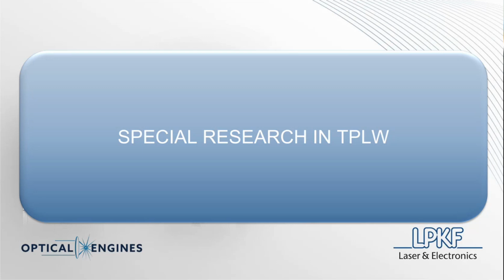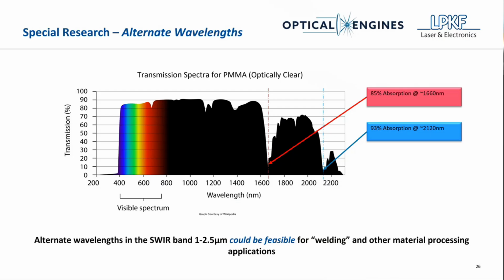So I wanted to cover a few special research topics in transparent polymer laser welding, some of the cutting edge stuff, and basically just educate and let people know that there are some options we have here, and we're working on testing. The first that comes to mind is working with alternate wavelengths. Not just 1940 nanometers, but looking at this transmission spectra and seeing that there were obviously valleys. Down at approximately 1660 nanometers, the absorption is much higher than that 30%. In fact, up to roughly 85%.